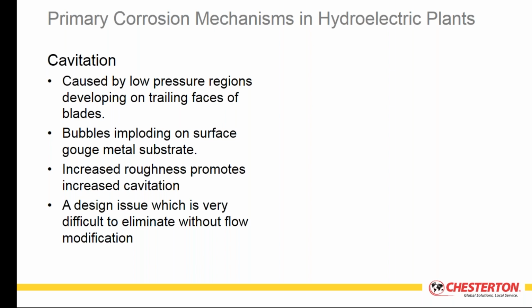Forces of several hundred thousand psi have been calculated, and they've also established that for microburst periods, extremely high temperatures are also generated across that surface. So those two forces of mechanical stress and thermal stress actually will accelerate the damage to the metal. Once that metal becomes roughened, you start to promote more cavitation, because cavitation likes to operate in rough, irregular surface regions where turbulent flow is more prone. So if you can keep a surface smooth and uniform, that will reduce the effects of cavitation.